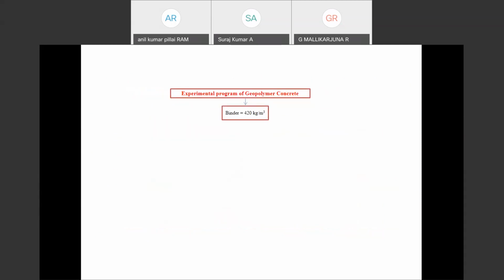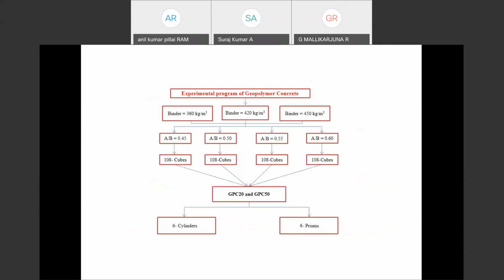to prepare the geopolymer also. And this is the experimental program we had planned, for 0.45, 0.5, 0.55, and 0.6. Why have we taken 0.45? Because we went for numerous trials. After that, if we go for a lower alkaline to binder ratio, automatically a workability problem arises. So in order to get water cement ratio curves the same as for conventional concrete, we produced some curves for this geopolymer. For that, we have taken alkaline to binder ratios of 0.45, 0.5, 0.55, and 0.6.